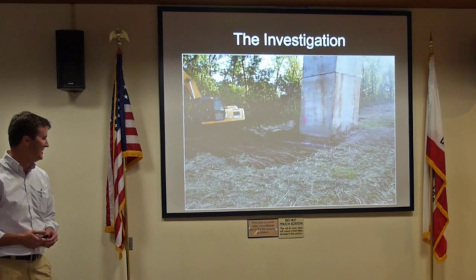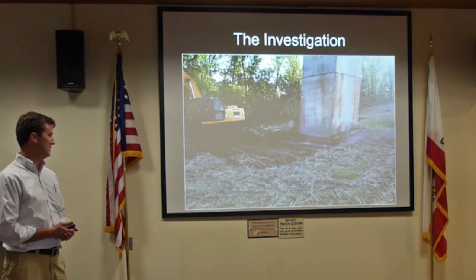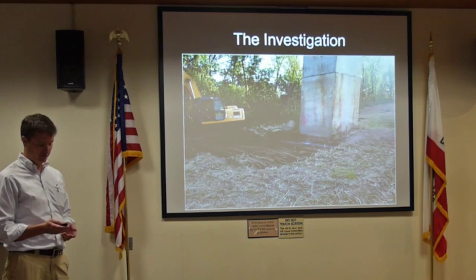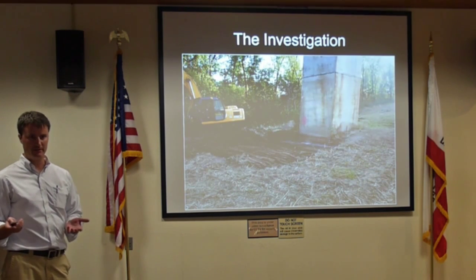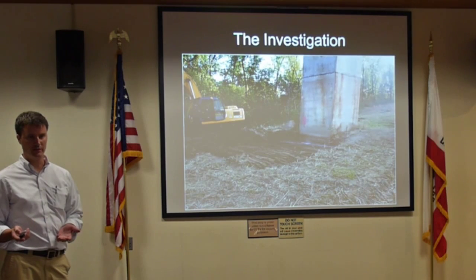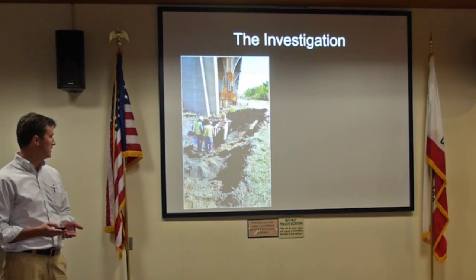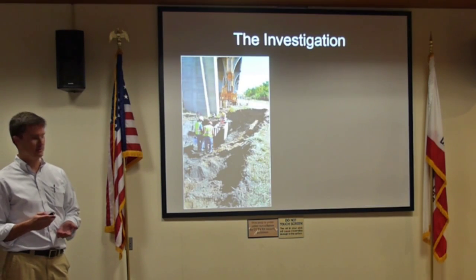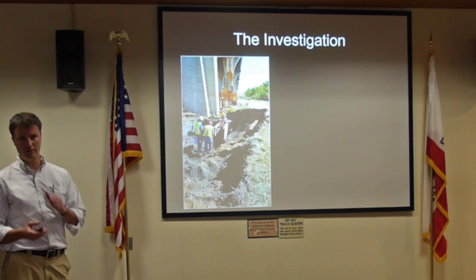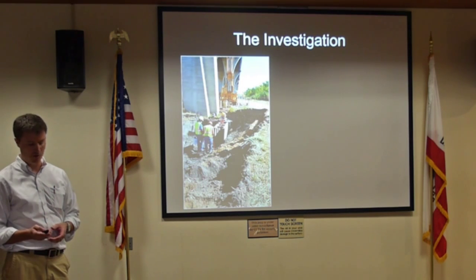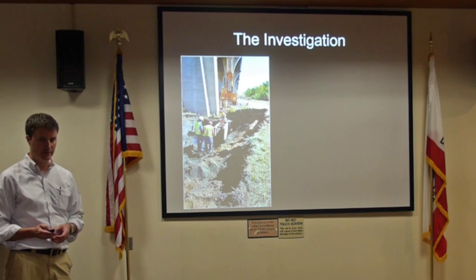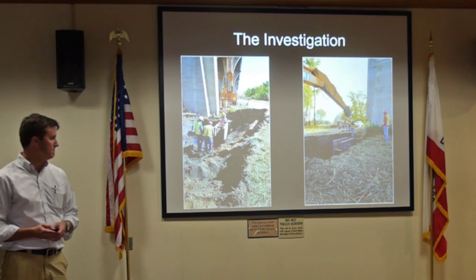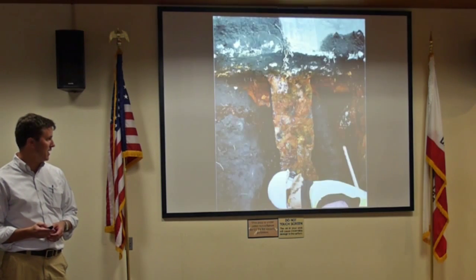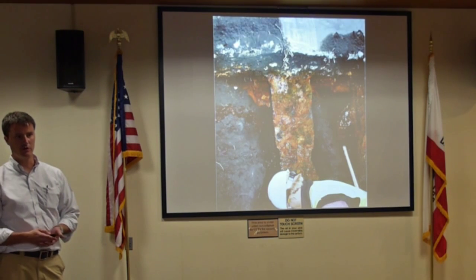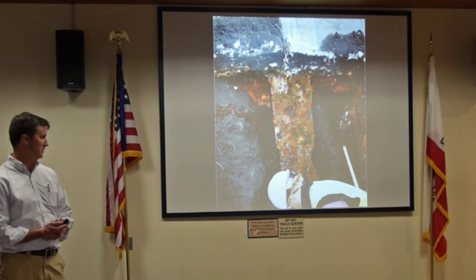That's right. So we started an investigation of the pier, and one of the first things, with this foundation issue, was looking at an excavation adjacent to the pier. The pier itself is basically about 6 foot thick concrete supported by steel H piles below. And as we progressed the investigation and got down to the bottom of the pier cap, this is what we saw in terms of the H piles below.